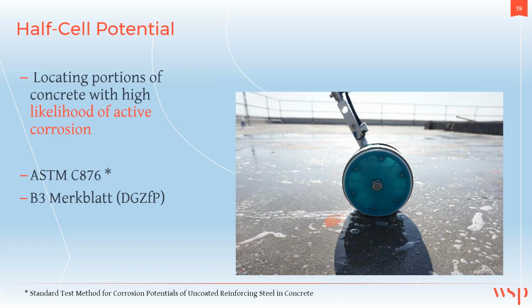This is commonly done in the field with what's called a copper sulfate half cell, which has a porous plug for the copper sulfate solution to ionically bond to the wetted concrete surface to create the electrolyte bridge. With this method, you can measure the relative electrical potential and interpret the likelihood that corrosion is taking place.